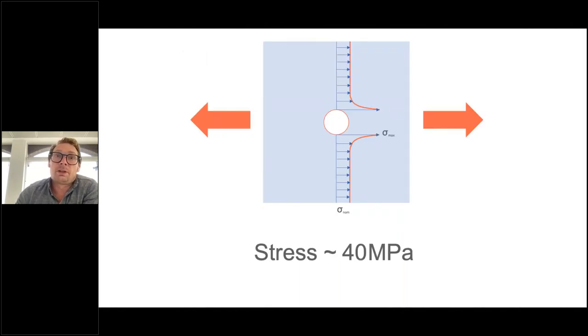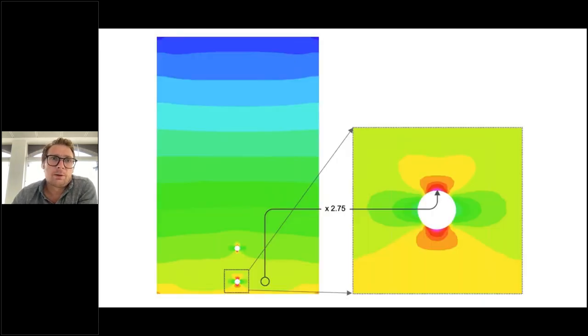But the problem with glass being purely elastic is that there's no deformation. So around the holes, we get a large stress concentration. So looking at a stress concentration of 40 in this example, it's really looking at a local stress, versus the nominal stress of 13 MPa. So this is our simple FE analysis of the panel for the bridge. We're just taking out a slice of the overall panel. And you can quite quickly see there's a 2.75 multiplication factor between a hand-derived stress of this as a beam and the local stresses within the holes.